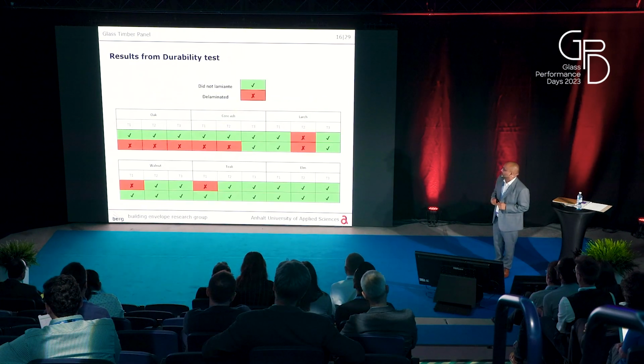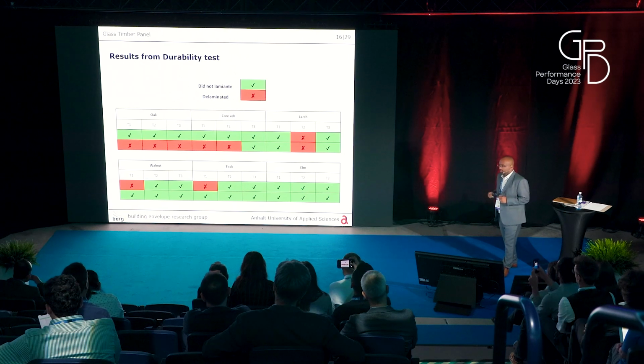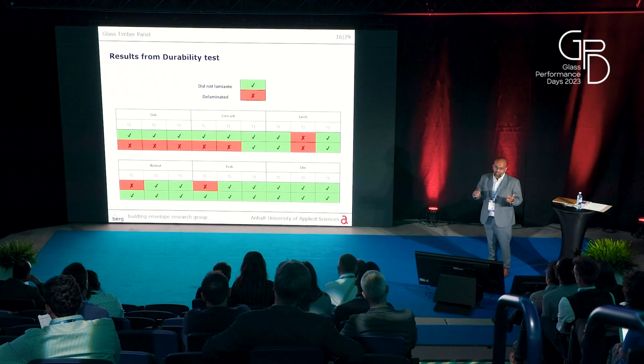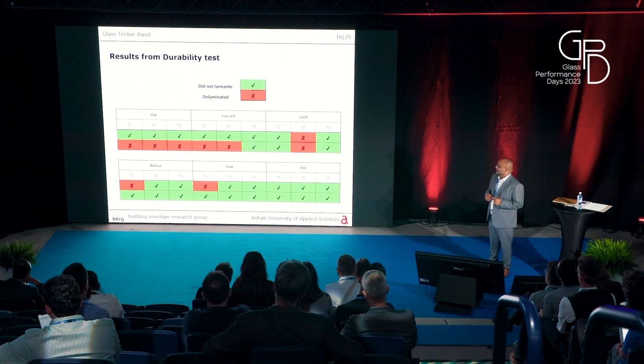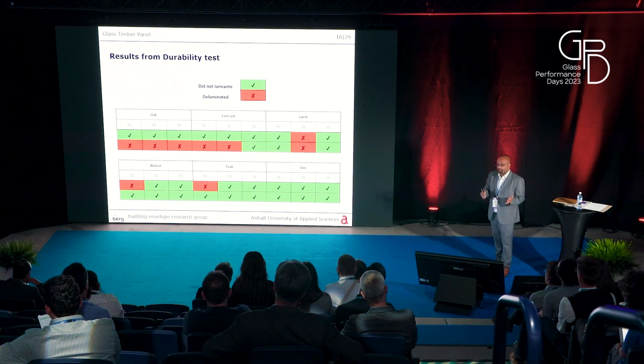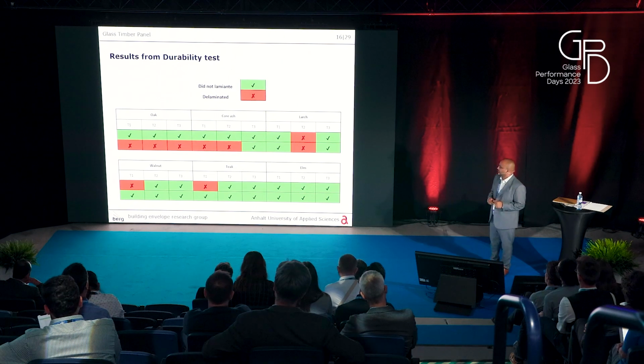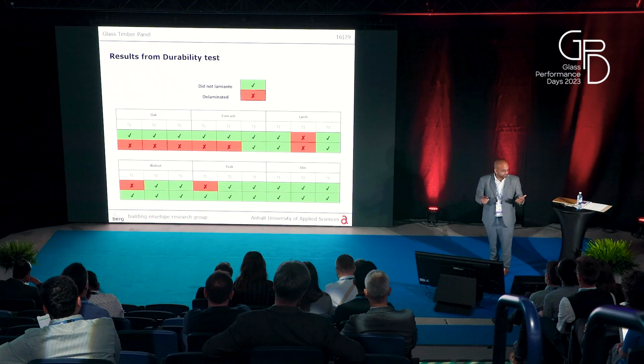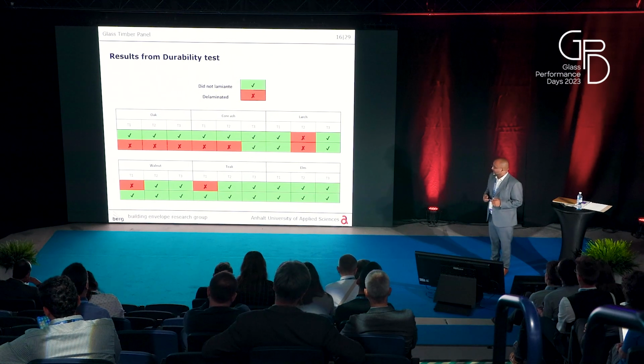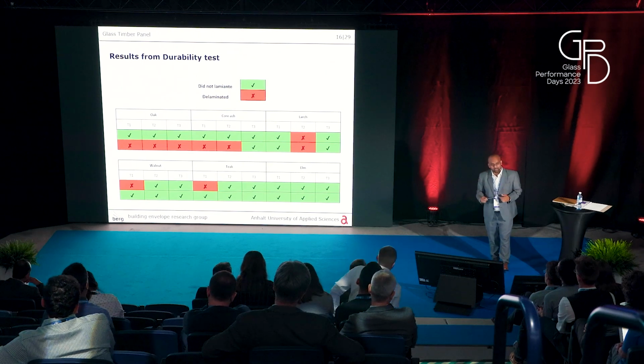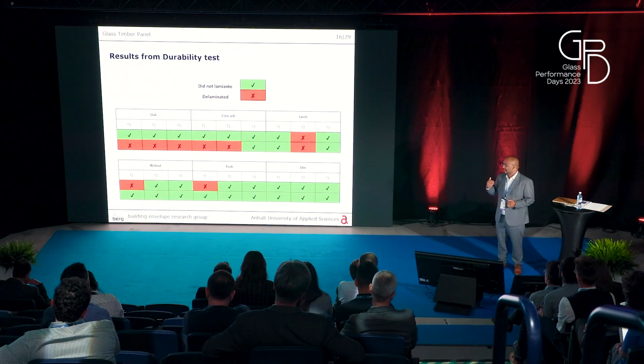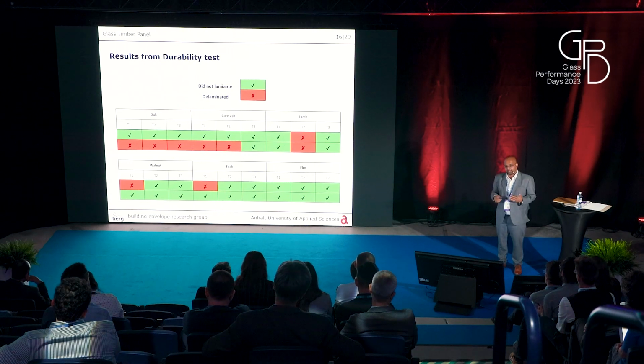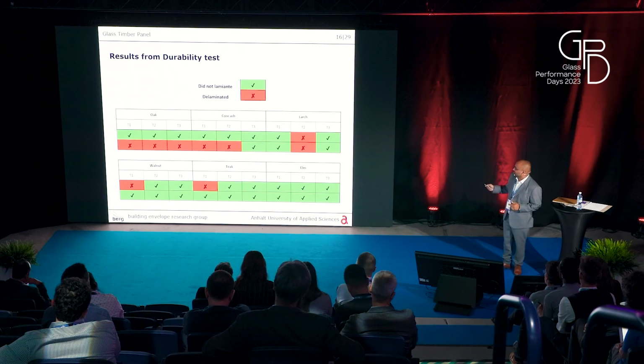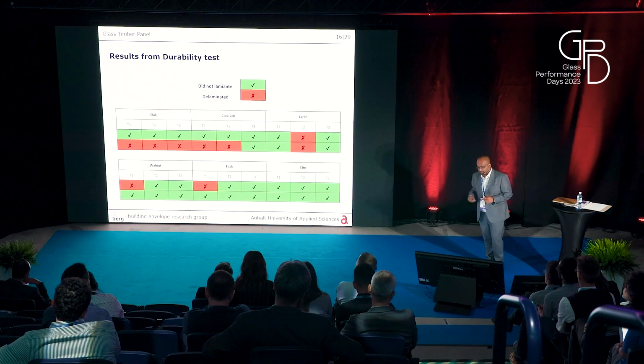So the results. We tested 36 samples, 2 samples of each wooden type, and out of which 9 samples delaminated, and there was no particular pattern of type 1 or type 2 or type 3 which delaminated, so it doesn't show any effect of the edges. And we should also note that it was an extreme test for interior application, because minus 18 and 53 degrees are not something that we actually experience indoors. So taking that into consideration, I think the results were quite good for durability.